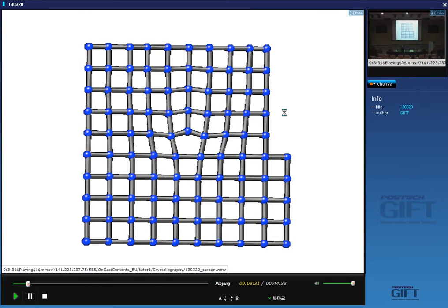If I have a very narrow gap, in other words, I've tilted the crystals only a little bit, then I put in a few dislocations. So the area of the boundary can be described in terms of a set of dislocations, in this case, edge dislocations. And the purpose of the dislocation here is to fill that space that we've created by tilting the two halves of the crystal with respect to each other. So this is an imaginary operation in the previous slide, where we cut the crystal in half and we found that there is space which we don't see in real life, and that's because that space is filled by dislocations.